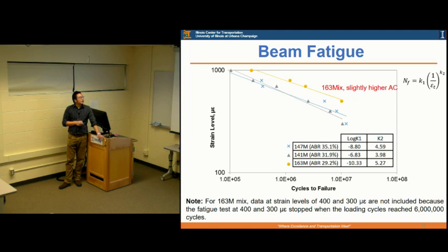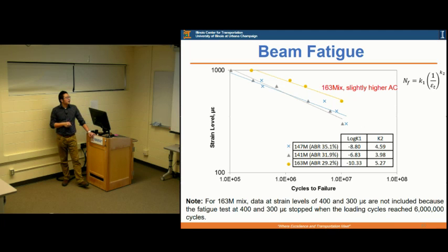They're showing actually better fatigue cracking resistance because they had higher cycles to failure. As I mentioned earlier, the 163 mix had a little bit higher asphalt content, about 8% versus 7.7%. If you have a little bit higher asphalt content, it's actually going to improve your fatigue resistance for mixes.